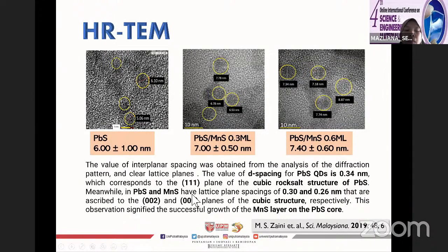For PbS/MnS, when we analyzed these samples, we measured the d-spacing at the center of the quantum dots and also at the boundary of the quantum dots. We got d-spacing values of 0.3 and 0.26 nanometer, and these correspond to the 002 plane in the cubic structure, which refers to MnS and the PbS core.